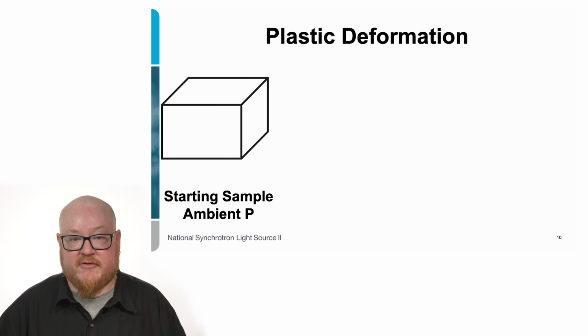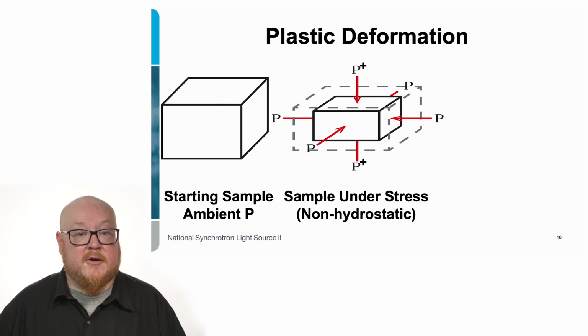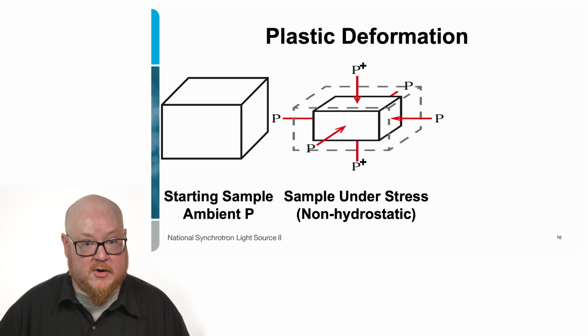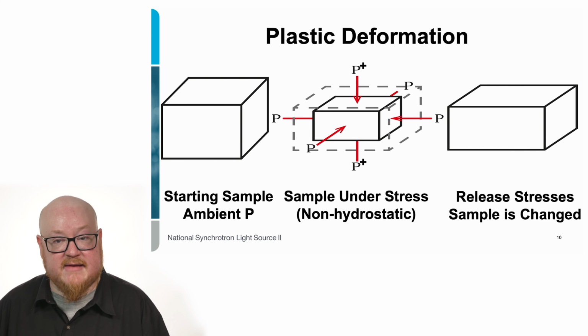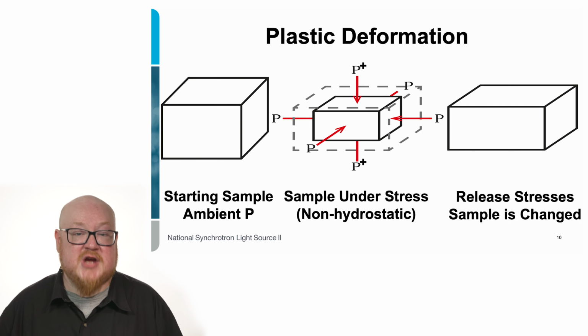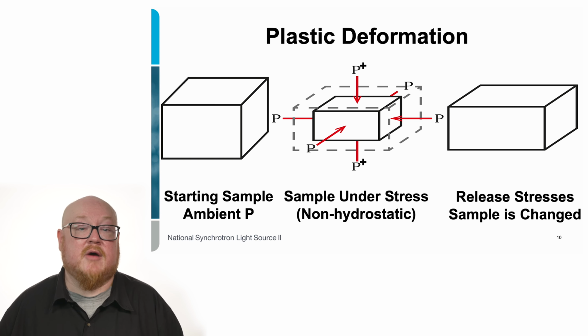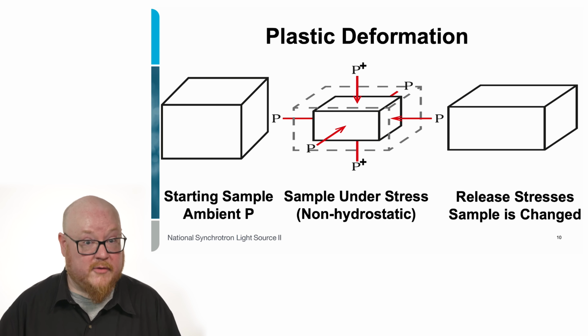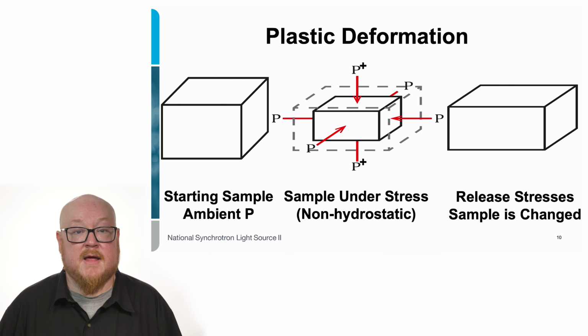However, in plastic deformation, which is what occurs during these forging processes, we start with the sample at ambient pressure, and then we put it under pressure, but it's not the same in all directions. And then once we release that pressure, the sample is changed in the shape and properties from what it was before we put it under those plastic deformation conditions.